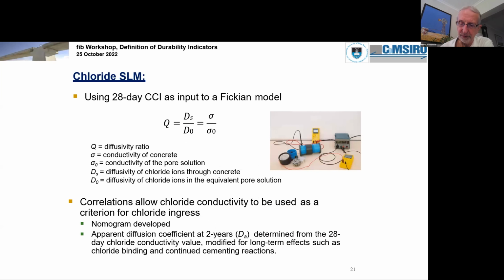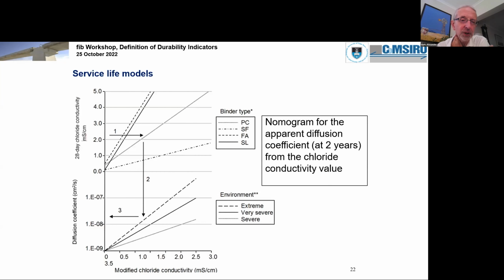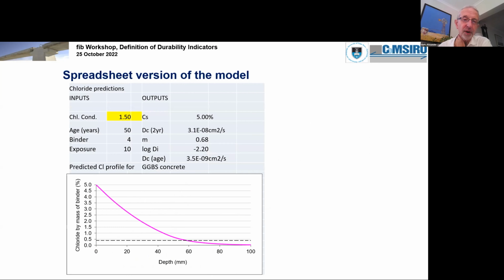The chloride service life model is based largely on the formation factor equation, the one that you see there. So in other words, if we can measure conductivities, we can infer diffusivities. And as I said, we need to allow for an age effect because of binding. And a nomogram has been developed in which one can enter the chloride conductivity value, move through the binder type and the environment, however you want to define that, and come up with a diffusion coefficient, which can then be applied in a service life model to check on the chloride profiles. And just to give an example of that, this is the spreadsheet. It's implemented on a very simple spreadsheet, which doesn't need much by way of computing power at all.